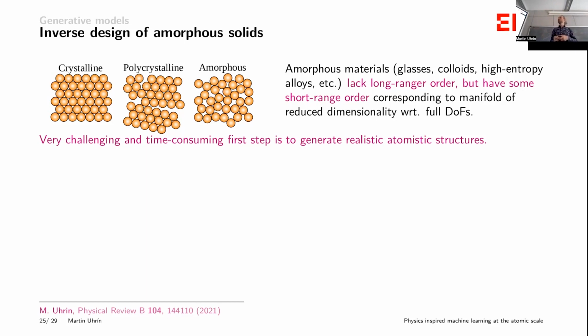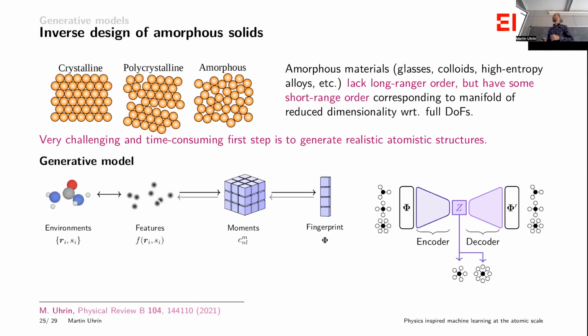And a lot of the time, we find that actually, no, that isn't the right one. The radial distribution functions we have from experiment don't match, or it's actually not stable. And you spend a lot of time doing these very expensive calculations, choosing different quench rates, and depending on the system, it can be a bit of an art to even find your final structure. And remember, that's just even the starting point. Once you have that structure, then you can calculate properties of it, do things from that building block. So it's really something that would be great to accelerate.